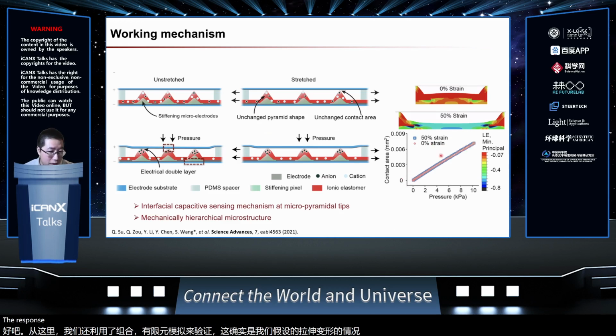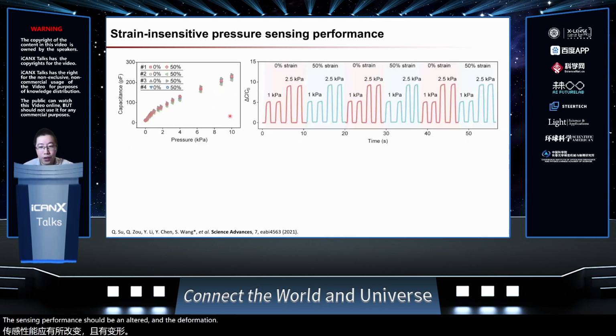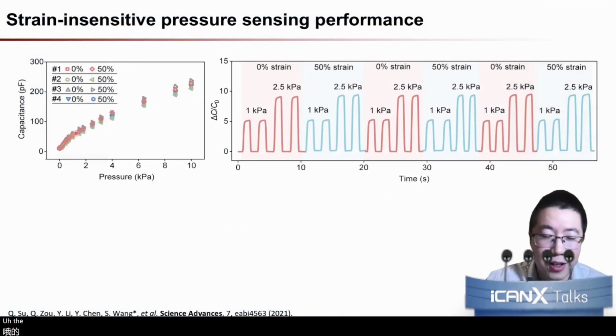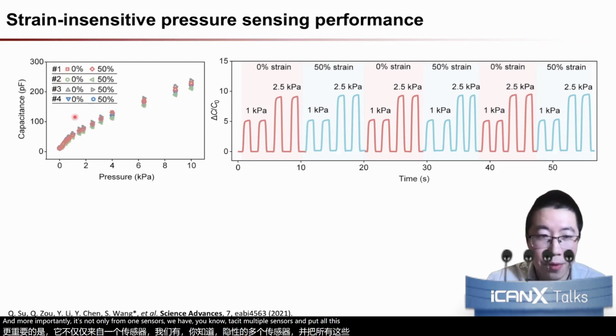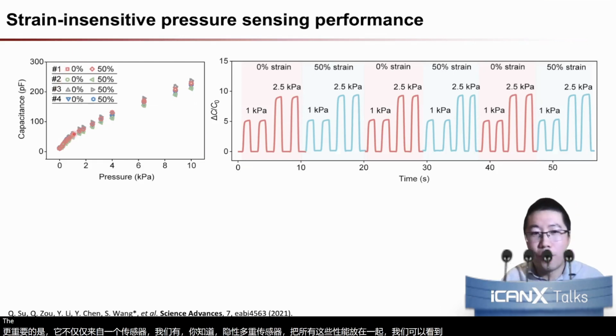The response curve of the contact area at this pyramid tip maintains the same relationship to the pressure, which indicates that the sensing performance should be unaltered under the deformation. So further, we have fabricated a number of devices based on this design, and as we can see, indeed the pressure and strain insensitivity performance have been achieved, and more importantly, it's not only from one sensor. We have tested multiple sensors and put all these performances together. We can see that they overlap very well with each other, right?